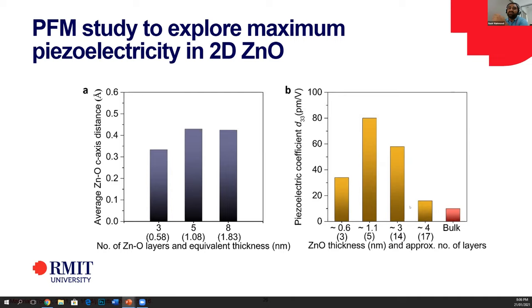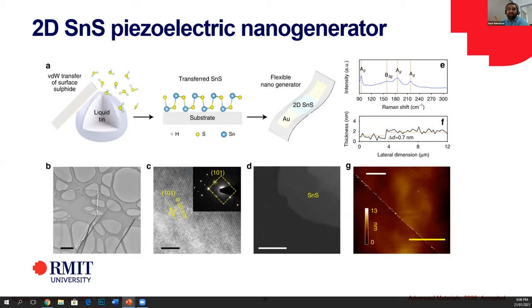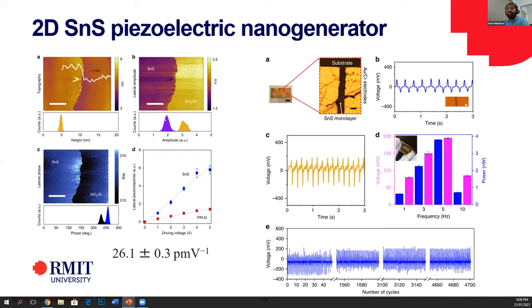Then we extended this to another material, tin sulfide. Normally, getting 2D tin sulfide is very difficult. But here we applied the same liquid metal method, and we easily got large sheets of tin sulfide. The characterization again shows highly crystalline sheets with very low thickness and very large surface areas. When we did phase change PFM studies, we found that this is also a very active material. So our aim is to develop materials which are very active.